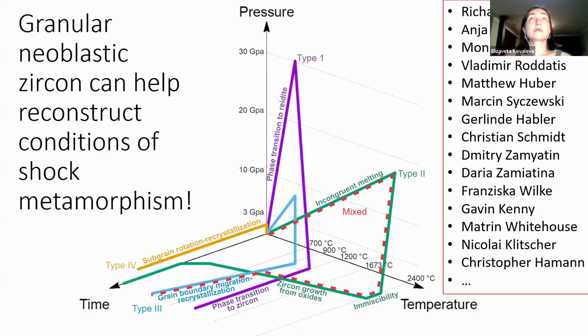So we can estimate peak pressures and temperatures. Okay, in this particular area, this is the peak pressure which was achieved. But we cannot really define the boundaries because, as I said, in one sample you will have a completely shocked grain and then a completely unshocked grain. So they experienced different deformation. But we can talk about the one which was shocked and which pressures it achieved, and that way we can identify the peak pressure. I don't know if that makes sense.